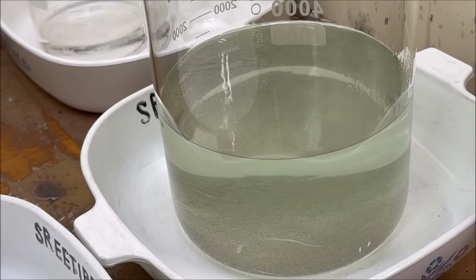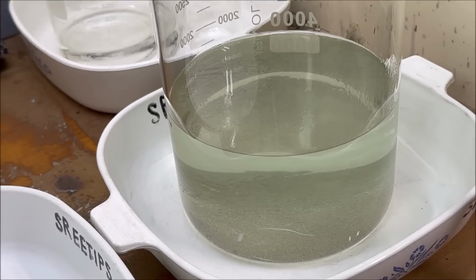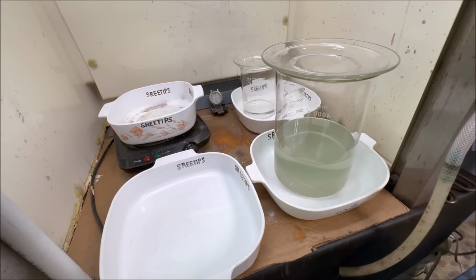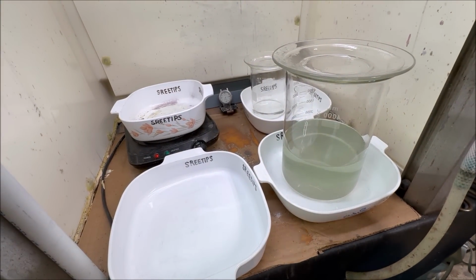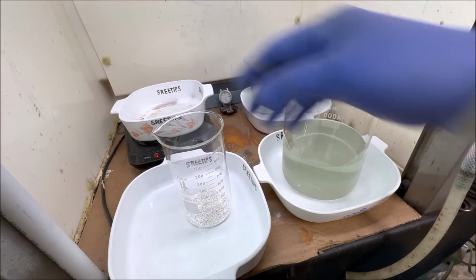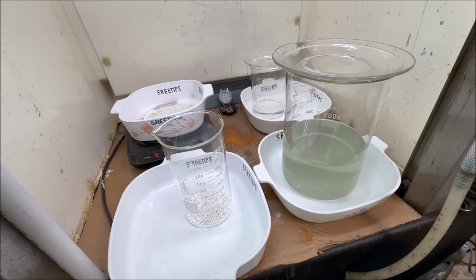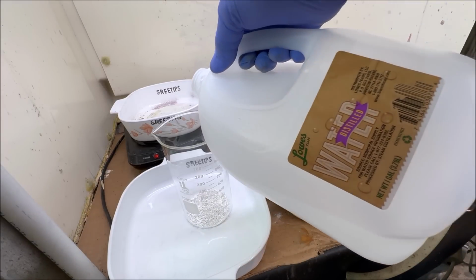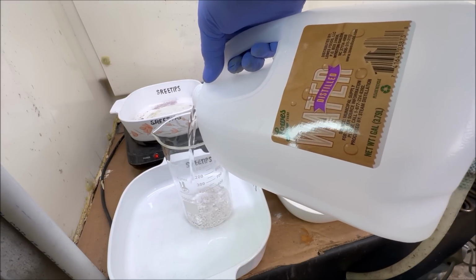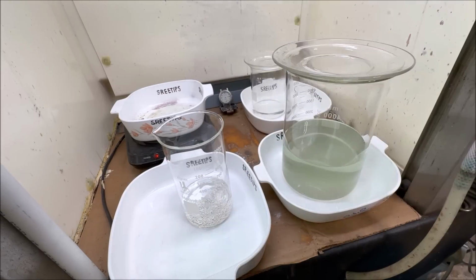You'll notice that the color of the electrolyte has a pale blue tint to it, which indicates that there's some copper in there. And since I used some of my own pure silver crystal in there, now I'm going to have to prove that it's not my crystal that has the copper in it. It was the silver bars that had copper in it. So we're going to dissolve a little bit of my pure silver crystal.